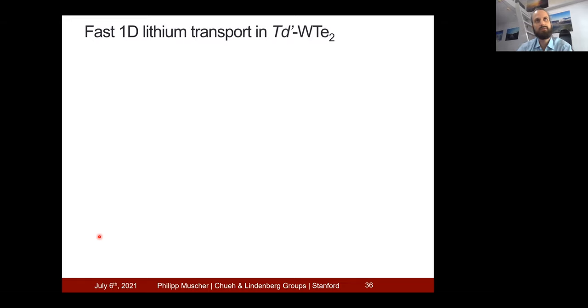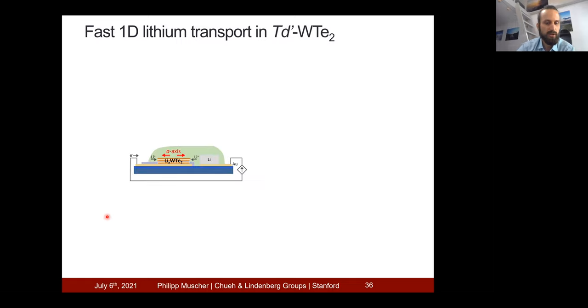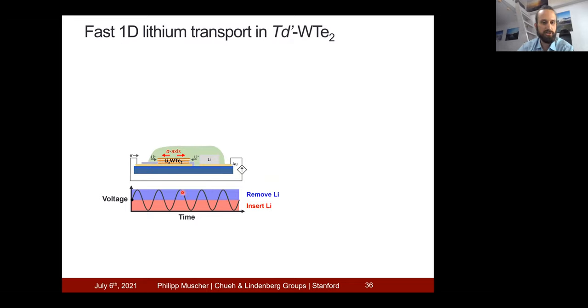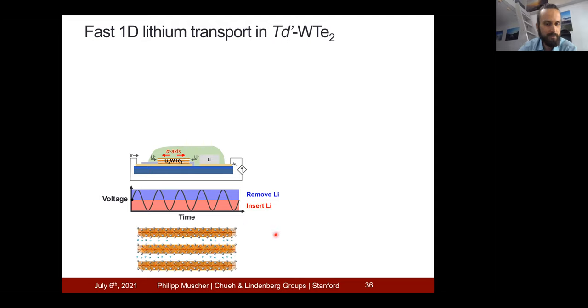So then with this, I wanted to know how fast can we actually switch this material? For this, I turned to an experiment where I again use this liquid cell platform, and I am applying a sinusoidal voltage between the two electrodes. I choose the voltage in such a way that in half of the voltage range, lithium is being removed, and in half of the voltage range, lithium is being inserted. So as I'm changing the voltage, you can see lithium ions will go in and out of this structure.